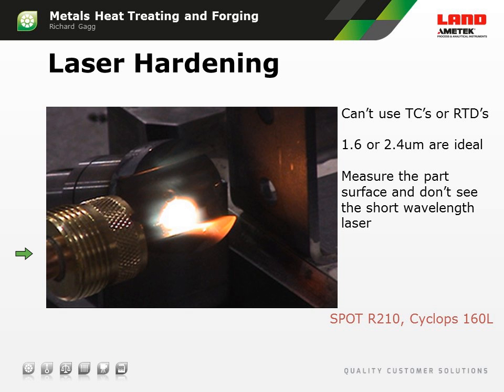Here's a very similar situation. A lot of people now, when they are hardening metal surfaces, use laser hardening, and laser hardening has a number of advantages. It's very rapid, so the heat is applied very rapidly to the surface of the material, and the heat penetrates a very short distance into the metal. The metal is rotated, and so this laser is passing that area and going on to the next bit of area and the next, heating, and then the substance of the product, the substrate itself, does the quenching to the surface. So the substrate of the metal actually becomes the heat sink that does the quenching.